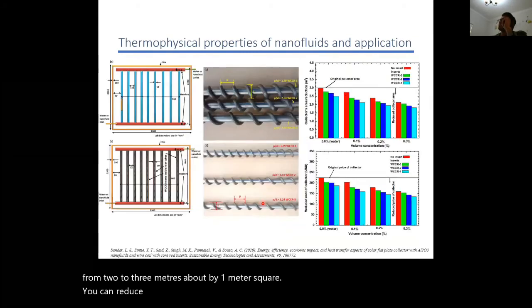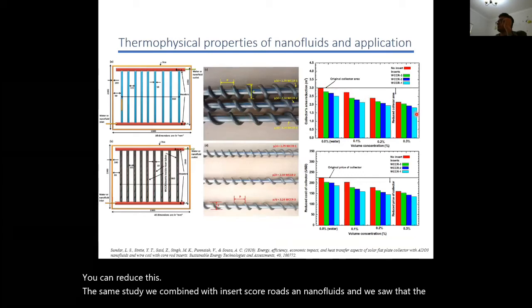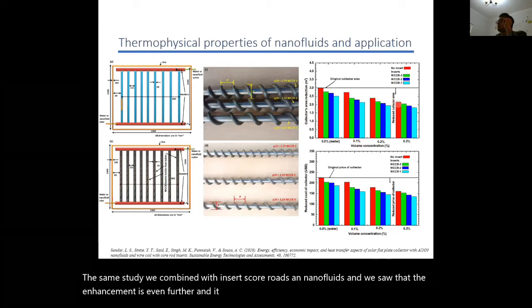The same study we combined with inserts, core rods, and nanofluids, and we saw that the enhancement is even further, and it can reduce the area even better compared to when you only use nanofluids, and overall heat transfer is increased.